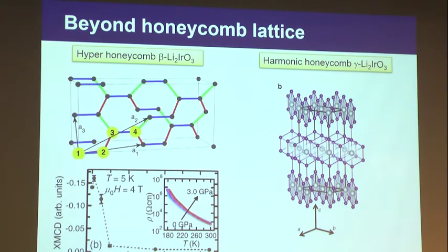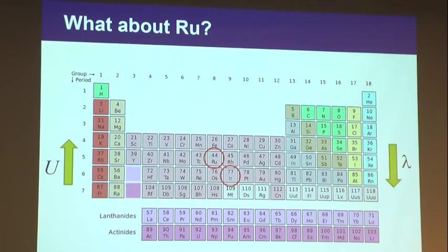But what's an interesting direction proposed in this work done by Hidenori Takagi's group is that if we put this material in a pressure cell and pressurize it using hydrostatic pressure, then the magnetic signal drops significantly around 2 gigapascal. And this is actually XMCD work done at APS. That is a strong signature, or indication, that magnetic order might be suppressed in the high-pressure phase, and maybe there you have a quantum spin liquid. The jury is still out, but that tells you one direction. So even if you have a magnetically ordered system, you can perturb it to achieve a non-magnetic or quantum spin liquid phase.